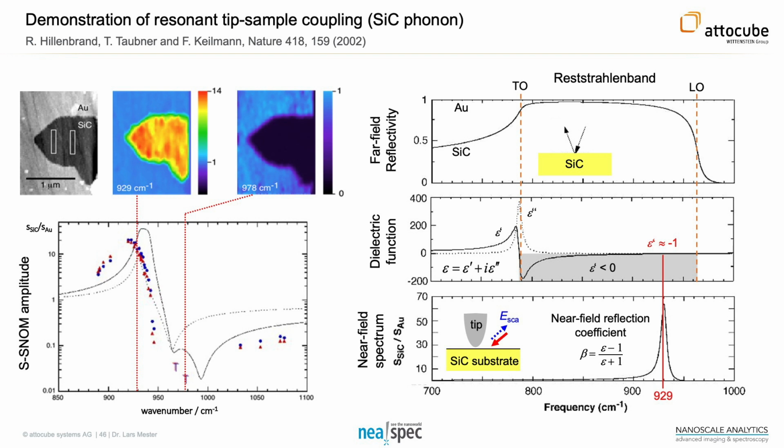The real reason is that we excite resonantly a non-propagating surface phonon polariton mode, which one could nicely see in a numerical simulation. The momentum mismatch is so big that it does not propagate away. When we saw this for the first time, we discussed it for years, and never understood what was going on. But now with the very thin 2D materials you can prove it, because these modes really start to propagate away.